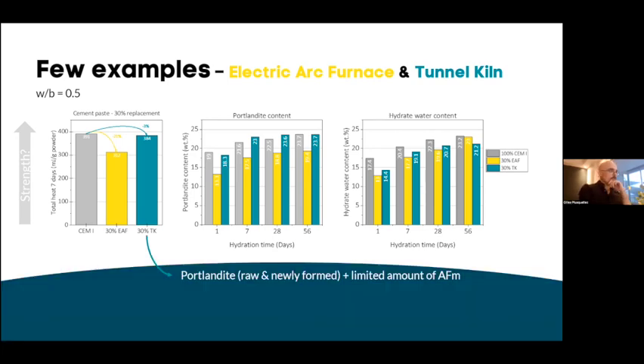So for the first steel slag, the tunnel kiln, what is mainly formed is actually Portlandite. We also have some in the original raw material, but some is clearly formed over time. And we also detected a limited amount of extra formation of AFM phases compared to the reference. This was done also by TGA and XRD, but again, it's not shown here.